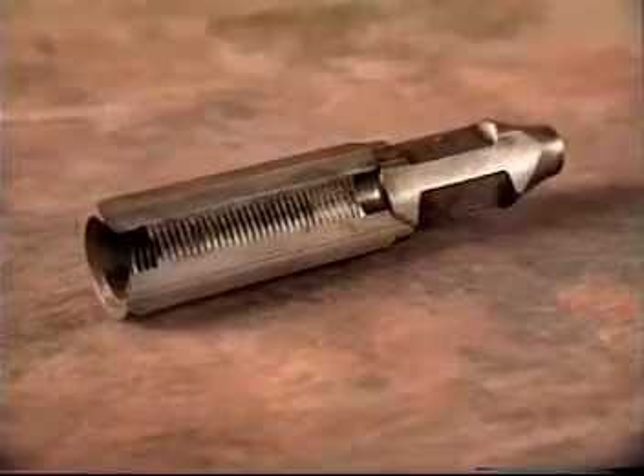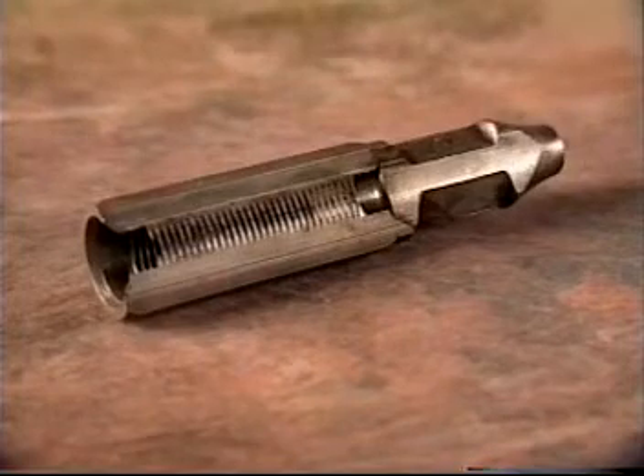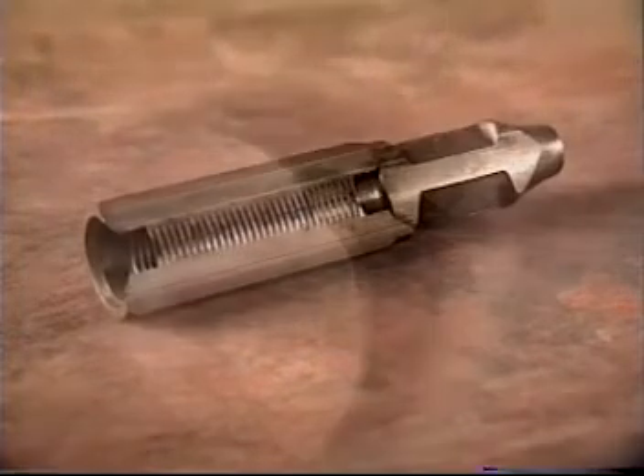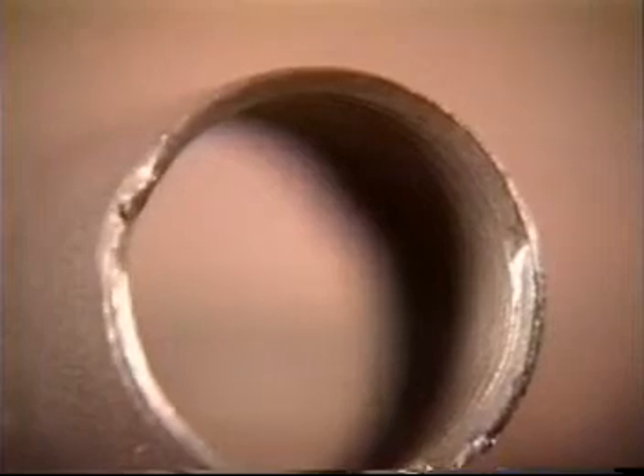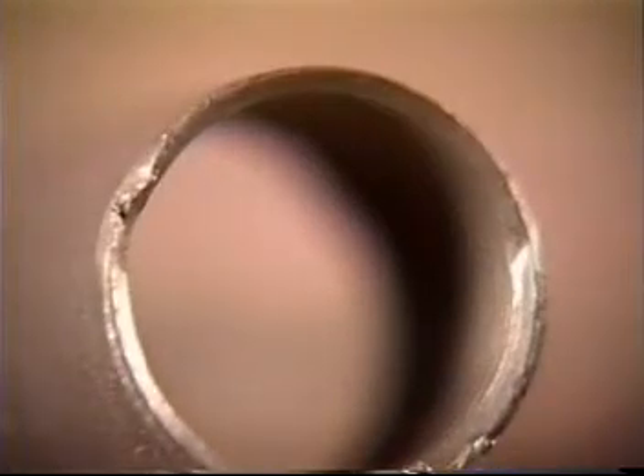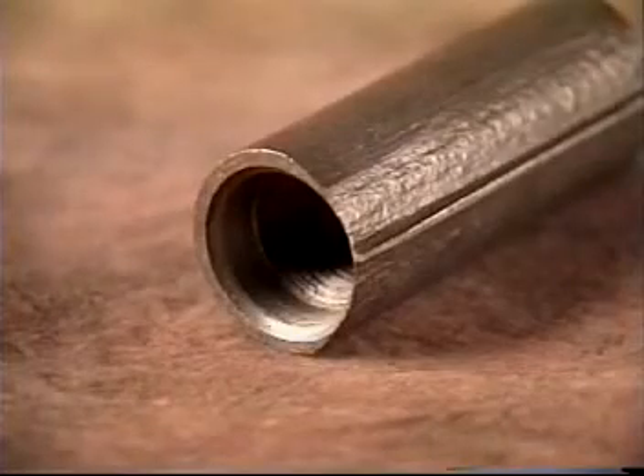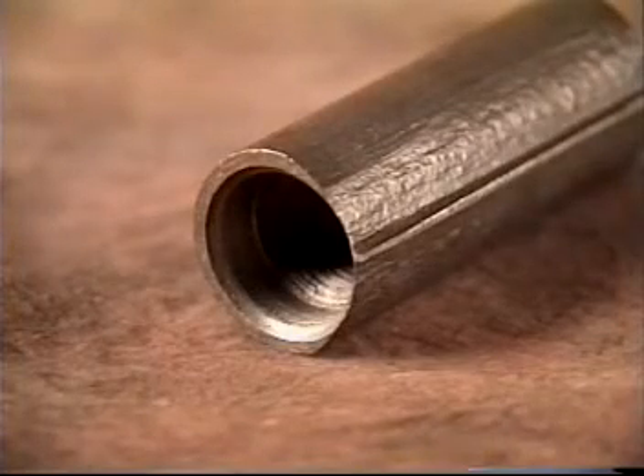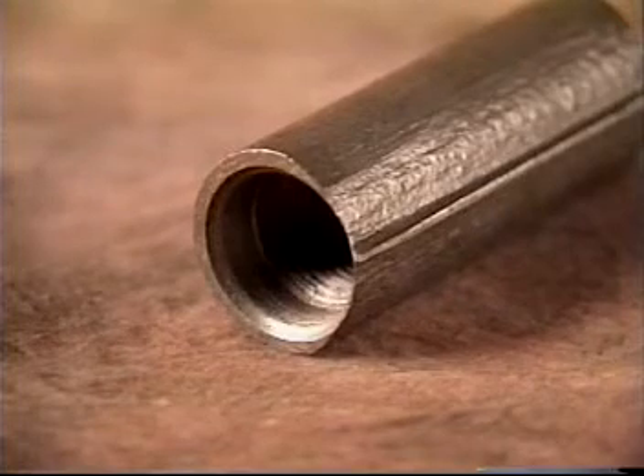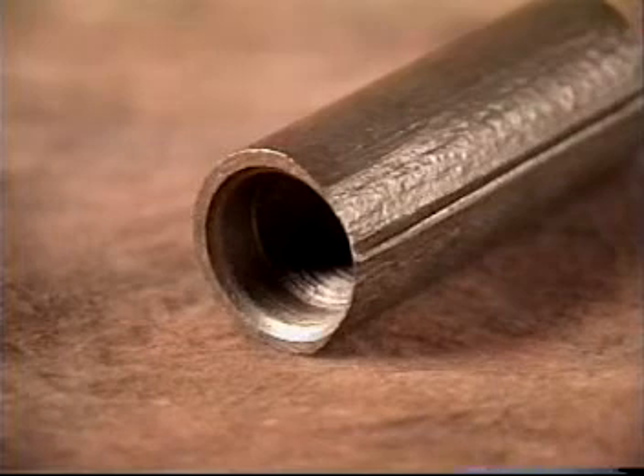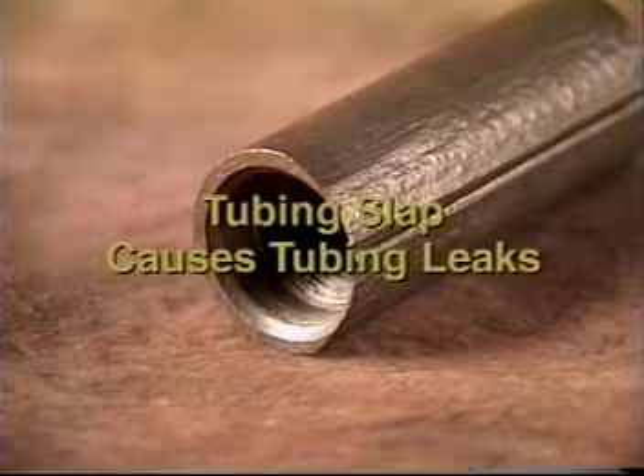Wear patterns on couplings that result from deviation will be equal in their length, width, and depth. Rod rotators will extend the life of couplings experiencing wear as a result of deviated well bores. When coupling metal loss extends below and into the rod shoulder, it indicates the coupling should have been replaced earlier. The combination of tubing slap and wear can produce some very strange wear patterns. When couplings slap the tubing, they effectively become work-hardened at the point of contact. When this type of ridge is being produced as a result of tubing slap and wear, it is also creating a potential leak in the tubing wall.